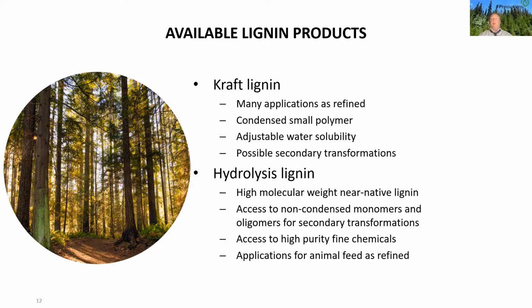Available products through both refinings: on the kraft side, the kraft lignin, which is today brought to many applications as refined directly from the mill. It's composed of condensed small polymers that are adjustable for water solubility, are transformable in secondary transformations, and amenable to many, many applications. On the hydrolysis lignin, the product is of higher molecular weight, a near native lignin, as close to natural as possible, wherein we have access to a non-condensed structure, easily amenable to break down into valuable monomers as well as functionalized oligomers. This gives us access to high purity fine chemicals, as well as refined applications, for instance, in animal feed and fisheries and so forth.